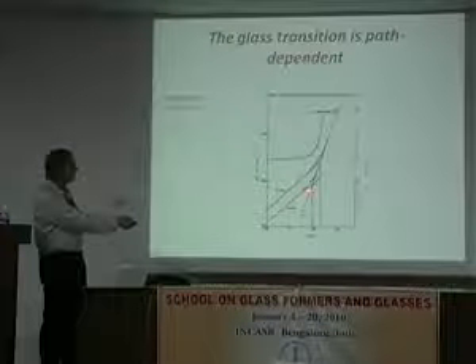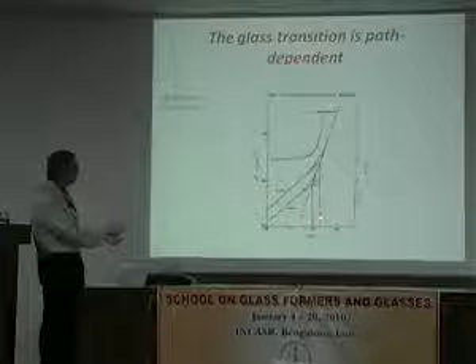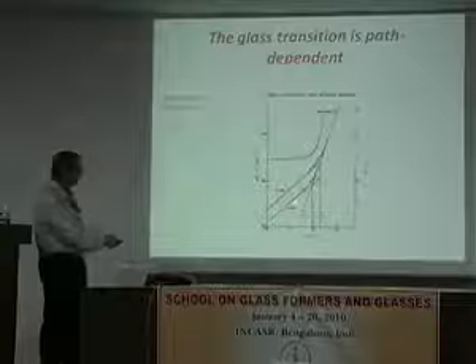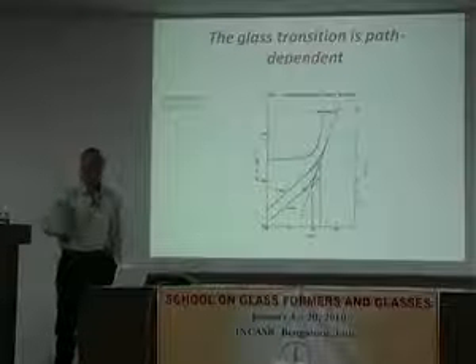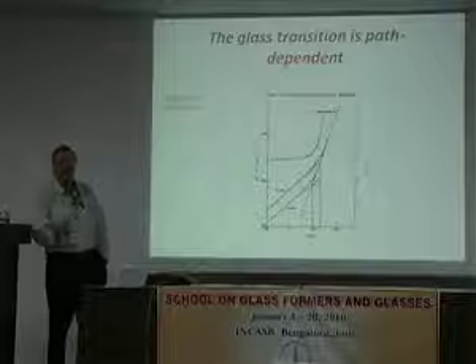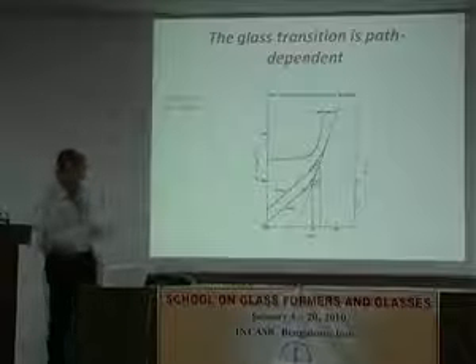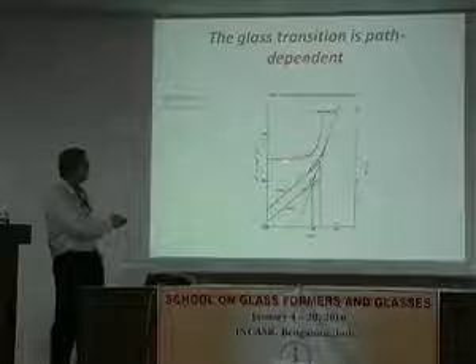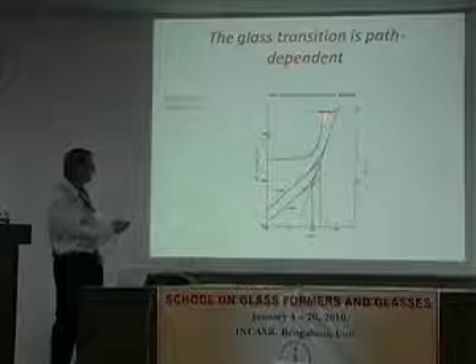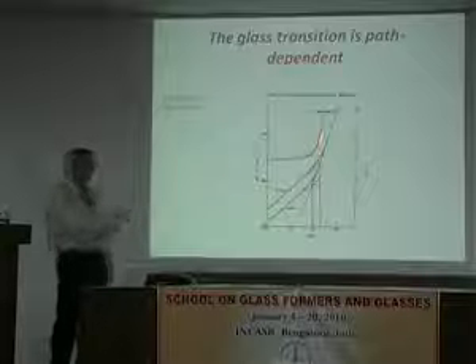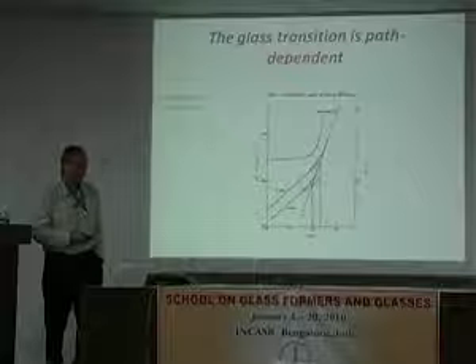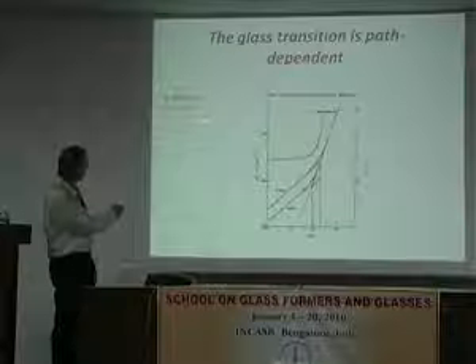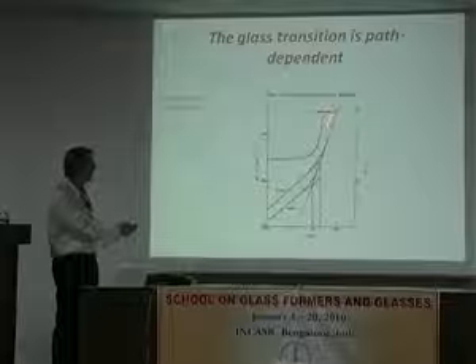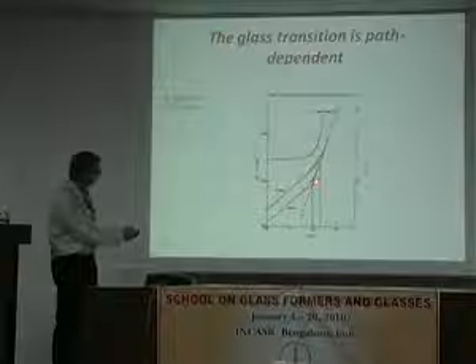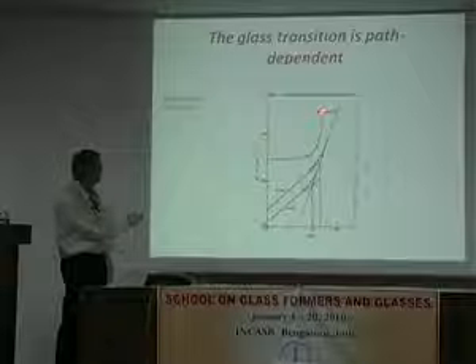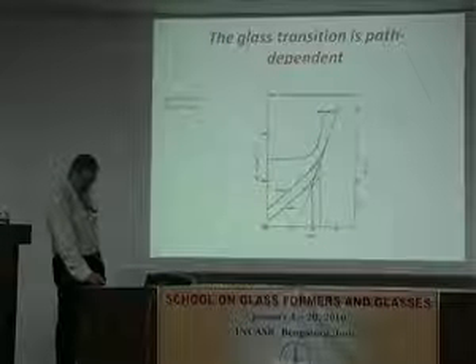So, but the thing is that what we see is that the Tg depends on how fast I went. And in the case of polymers, this dependence is about maybe 3 to 5 degrees Kelvin per logarithmic decade of cooling rate. And then we see this sort of classic signature in the coefficient of thermal expansion for one of these curves, which makes it look like it's sort of a thermodynamic transition of second order. Okay, but I think the important thing is it depends on rate or time, and this curve would shift if I plotted the slower experiment. I would obviously get a shift to lower temperatures when I plotted that slope, that derivative.